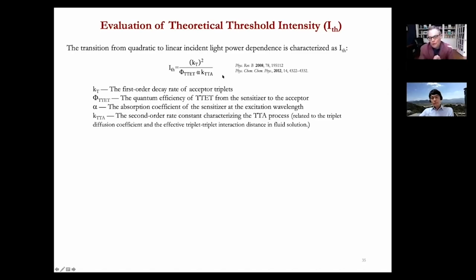The problem that comes up with this, one of which is the inner filter effects that you also don't see here, which are really bad from the Soret band of a porphyrin. That's the first major limiting factor in using porphyrins as upconversion sensitizers. When you're upconverting into the blue, you're contending with extinction coefficients that are hundreds of thousands, and that's just really hard to mitigate. You get a lot of light reabsorption by the porphyrin, and of course that's not accounted for here. That's really the first problem.